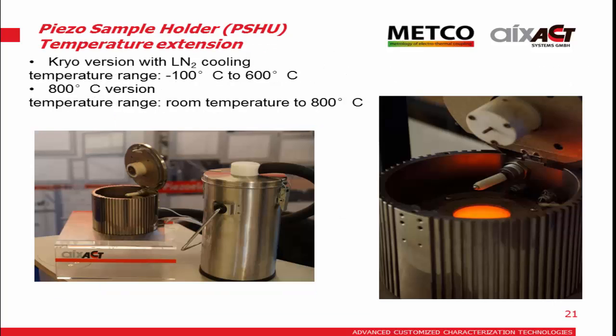Within this project we developed the higher temperature capabilities. We had a version from -100 degrees C to 600 degrees C, and the main limitations are actually the materials that you can use. For going to high temperatures, you must have a material which still establishes good contact over the whole temperature range without degradation. And if you put in the sample and pick it out, you must not deteriorate your setup. But being able to measure many samples without destroying the electrode materials.